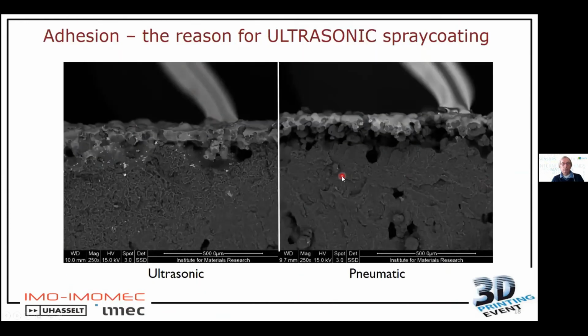If we do the cross section, then we can see a difference between ultrasonic spray coating and, for example, pneumatic spray coating. And that's the reason why ultrasonic spray coating is so interesting, because of the low speed of these droplets that go to the substrate. These droplets have the time to capillary penetrate into the porous surface of your 3D printed part. That means that you fill your pores rather than, with pneumatic spray coating, just adding some material on top of your 3D printed part. That is shown here, which means that you have, let's say, better adhesion properties.